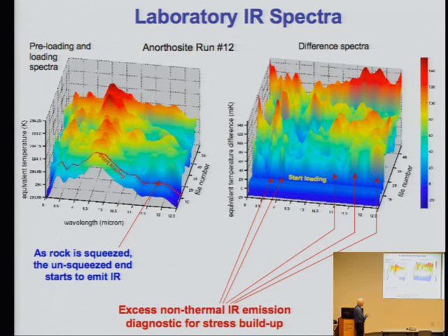And this band here, believe it or not, is at 930 wave numbers. It is exactly where you would expect the last transition from the vibration excited state, quantum state 1, to the ground state 0. And then you see the series of other bands at longer wavelengths, and we don't see any further because this was done in air, so we get cut off by the moisture and CO2 in air. All these experiments have to be repeated in pure nitrogen and so on.